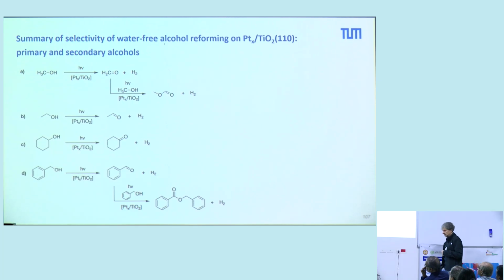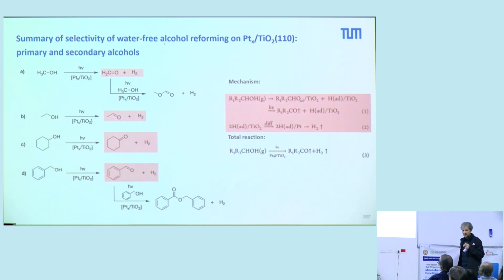Now you can ask the question, is this a general mechanism? Can we apply this to other alcohols? And indeed, we did study many alcohols. Methanol, ethanol, and then we have these species here. And you see that for all these primary and secondary alcohols, we have exactly the same mechanism. We always adsorb the alcohol as methoxy. We have the formation of aldehyde, and then we have the thermal production of hydrogen in a very selective way.